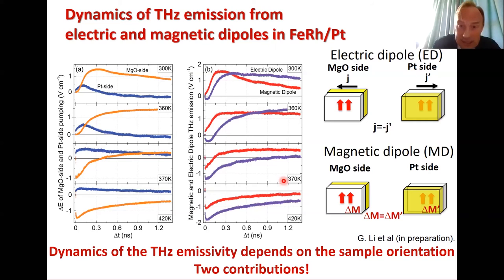Then you decrease the temperature, and you can see here that this negative part coming from demagnetization slowly disappears. It disappears together with the disappearance of the ferromagnetic phase in iron rhodium, and then a positive contribution appears, and this positive contribution corresponds to the increase of the magnetization in the medium.